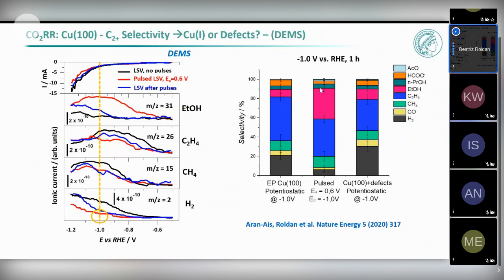And now if we take this sample, which is rough, but we run the reaction at constant potential afterwards, we don't have any copper plus anymore, and we see that this affects very strongly the production of ethanol. So what we learn from this is that, yes, ethylene is favored when you have 100 facets, but if you have a defective surface and copper plus coexisting with metallic copper, you can increase the amount of ethanol.